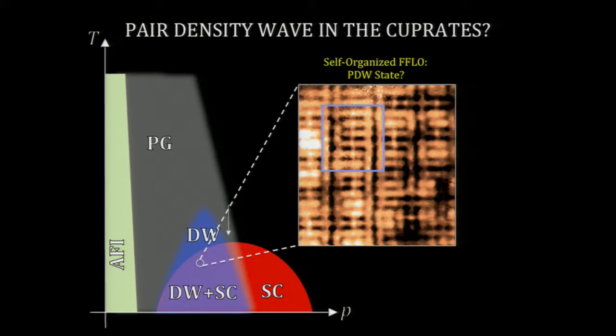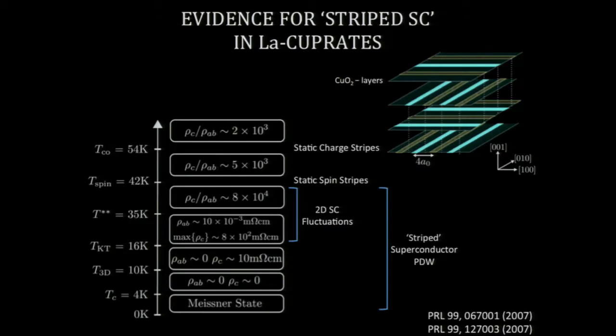So the question is, is this thing we saw with regular STM tunneling possibly coming from a pair density wave state, a modulated superfluid state? But the difference being that when the 1960s version was proposed, it was in a magnetic field. Is it possible that in the cuprates there's a self-assembled one, that you don't need a magnetic field, that it spontaneously emerges because it's trying to mix the quantum orders and the classical orders of the electronic liquid crystals and the superconductivity? So there's lots of evidence. The same people that proposed these electronic liquid crystals looked at the lanthanum-based compounds and saw that this cascade of transitions that happens in these lanthanum-based compounds could be explained if the layers, the copper-oxygen layers in those compounds, had a modulated superfluid, but which were orthogonally oriented.